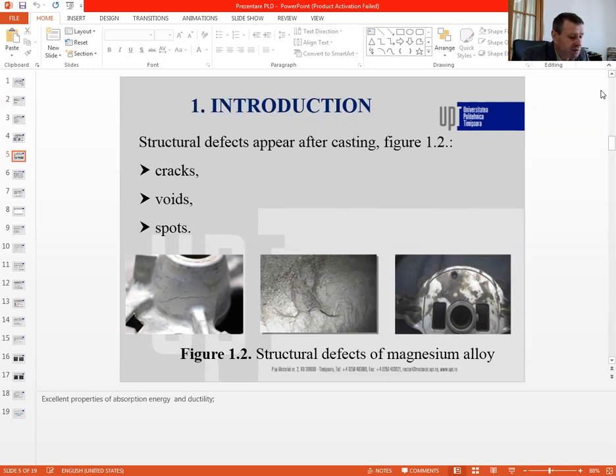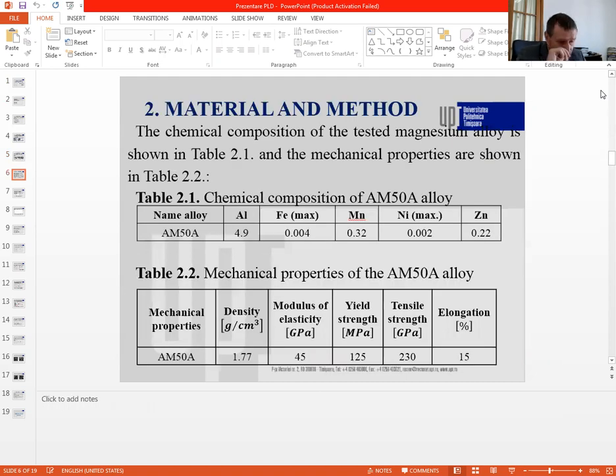This paper analyzed experimentally the effect of size on the fatigue duration of the magnesium alloy, considering the defects resulting from casting and the quality of the surface resulting from cutting. The material analyzed in the paper was the magnesium alloy, having the chemical composition presented in table 2.1 and the mechanical properties in table 2.2.